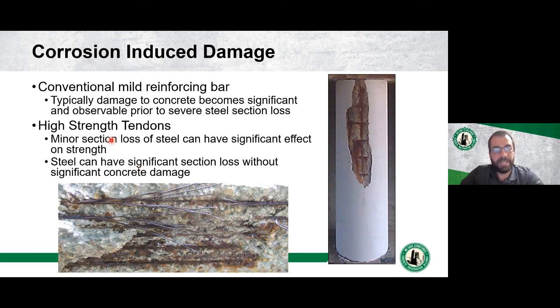However, with high strength tendons, so precast post-tension elements, we can have significant section loss without a lot of concrete damage. Here's a pre-stressed beam on the bottom here, and we can see that once the spall has formed, the strands are completely broken. In order for enough corrosion product to be formed to cause the spall, there was such high section loss of those strands because they're so small and under a lot of stress, you don't create as much iron oxide as you would with a conventional bar.